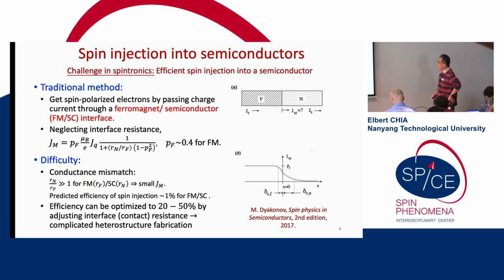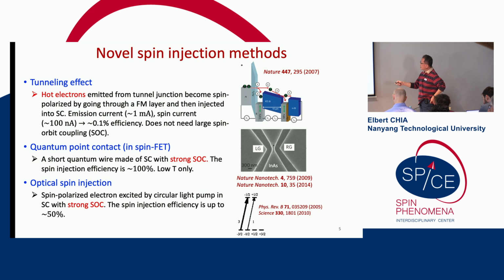A challenge in the spintronics community has always been whether it is possible to inject spins from a ferromagnet into a semiconductor. And because of this conductance mismatch between these two materials, the spin injection efficiency is always very low, of the order of 1%, for example. And various efforts have been done to try to increase this efficiency. So some groups use the tunneling effect, but the efficiency is still extremely low. Some other groups use a quantum point contact, but this is only possible at very low cryogenic temperatures, and other groups use circularly polarized light.